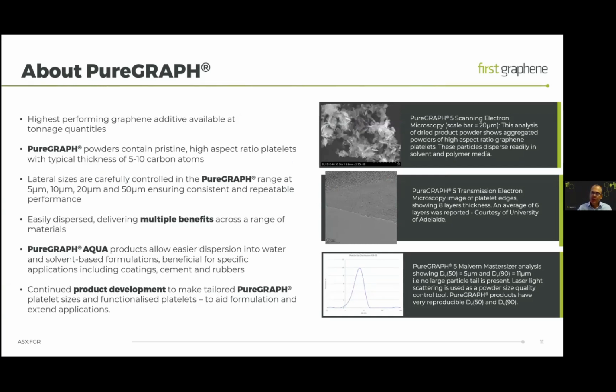The PureGraph product that we manufacture is a really interesting material because it is high aspect ratio, thin platelets, and we allow a small amount of oxidation at the platelet edges, which means that the platelets are easily dispersed and available for functionalization also. So we believe it's the highest performing graphene additive that you can buy in tonnage quantities. As I said, it's a pristine high aspect ratio platelet.